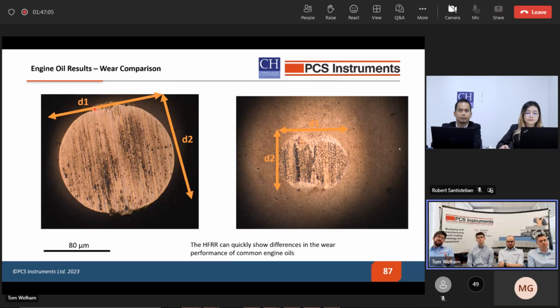So this was taken with an optical microscope, but like I've said, you can use white light interferometry, which gives you a much more detailed view of the 3D data of the wear scar. And we can work out the material volume as well using simple maths to work out how much, based on the size of the wear scar, how much material was removed.